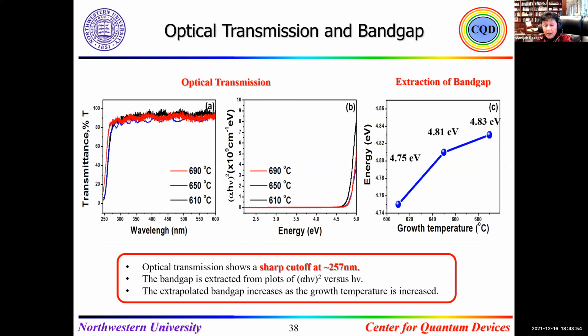So we did the variation of transmission, as you can see here, from 690 to 610 - the energy gap didn't change much. It's between 4.83 electron volts and 4.75 electron volts. You see that's a very, very little change.